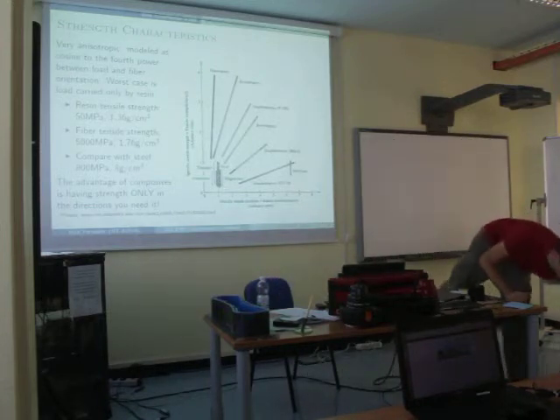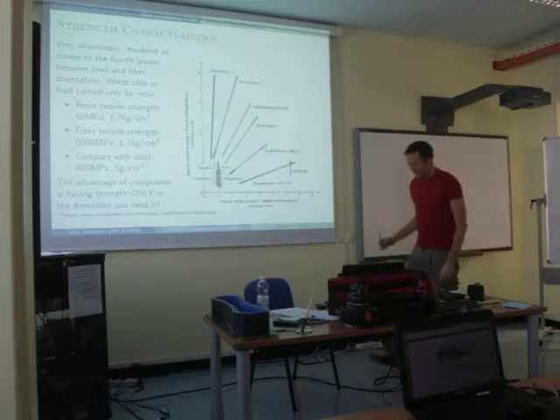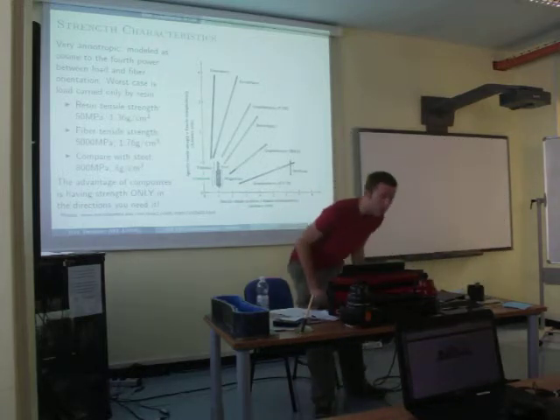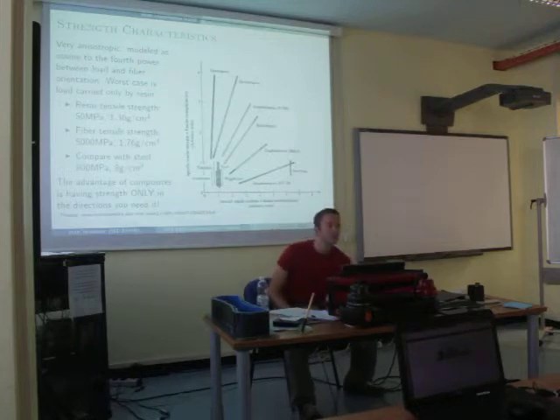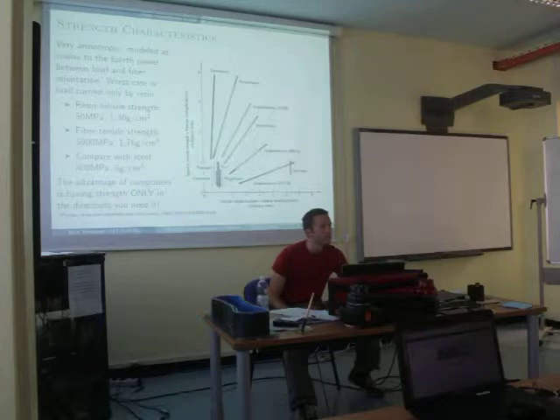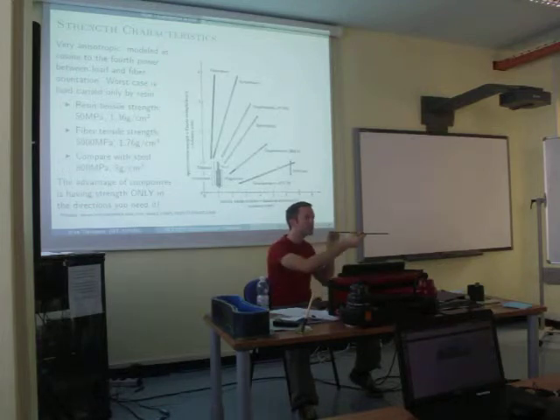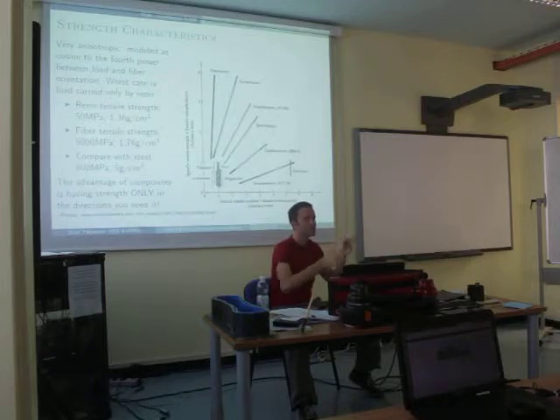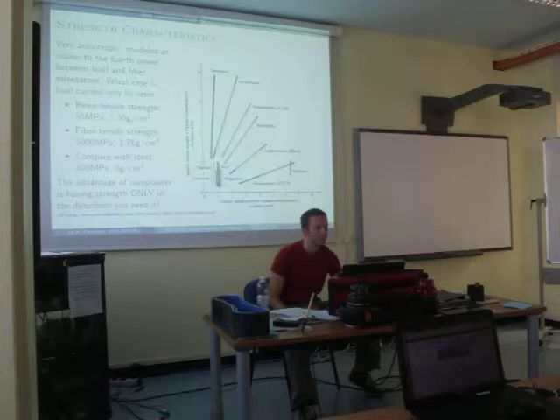So the strength characteristics are very anisotropic. In the direction that the fibers are running, these materials are very, very strong. In the other direction, they're not strong at all. So the material is fundamentally different from metals and crystals and things that we're normally used to in engineering. I've read a paper where they described the strength as the cosine to the fourth power of the angle between the direction of the load and the direction of the fiber orientation. So you get full strength of the fibers if the load is in the direction of the fibers. This is a fiber and you're pulling that way, full strength. If you're pulling at an angle and the load is this way, the strength is going to drop off pretty quickly.